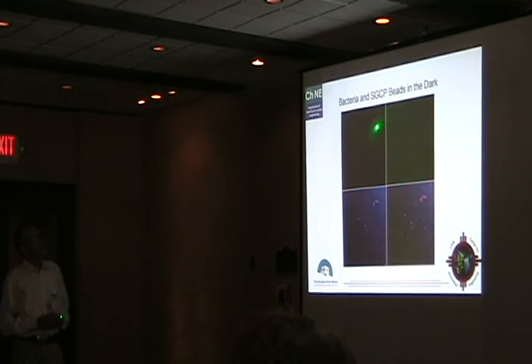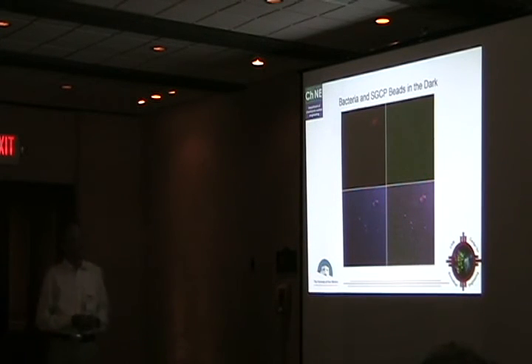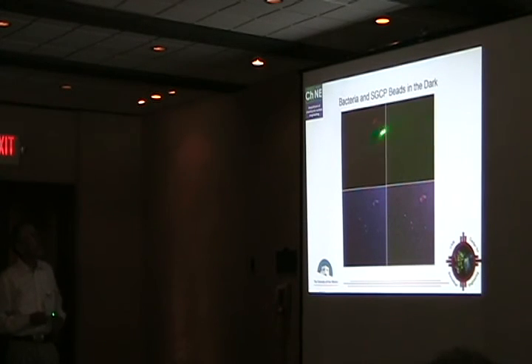Here are different confocal fluorescence images. Here we look at the polymer fluorescence. Here's a wavelength where the red dye emits. Here's the wavelength where the green dye emits, and then this is a composite. And so you can see clearly the polymer bead, which is surrounded by several bacteria. Typically we find 7 or 8 will surround the 5 micron bead. And you can see this is where the bacteria and the beads are incubated in the dark for an hour. And you can see there's no evidence of killing of the bacteria. Viable bacteria are seen here, and also viable bacteria that are on the beads.